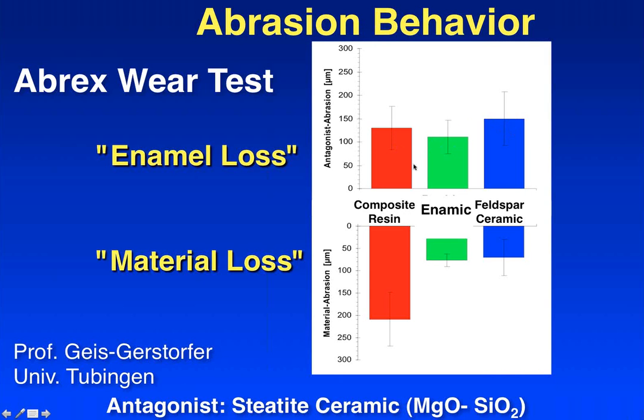Now let's look at material loss, which is a problem with composite resins. You see the composite resin lost the most material, so it's not a very stable material in the mouth as far as wear goes. You look at the Enamic and the ceramic, they're basically the same, and they are significantly less than that of composite resin.